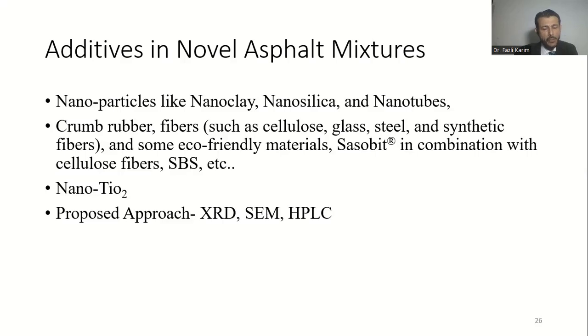So TiO2, on one side, improves the performance, but on another side it forms a coat or cover around the crumb rubber or nanoclay particles and helps them to be detected during the SEM process. When it forms a cover, during the SEM process it is usually detected as a yellow band, and it easily lets us know the extent up to which nanoclay or crumb rubber or any kind of additive can diffuse. So it is also very good to detect the extent of distribution of additive in the asphalt cement or even in the asphalt mixture.